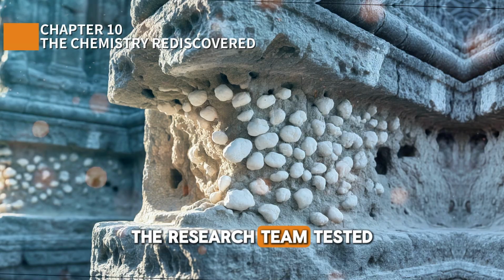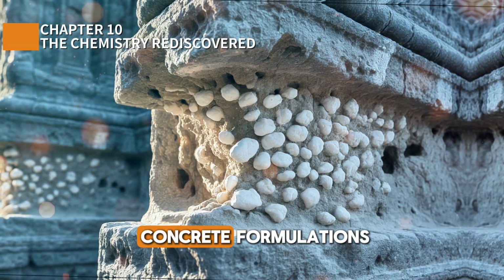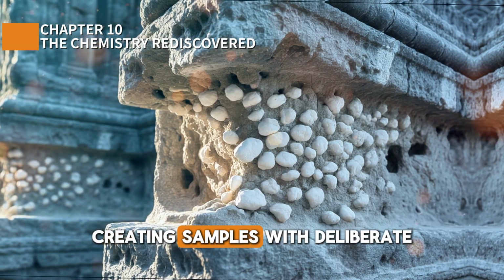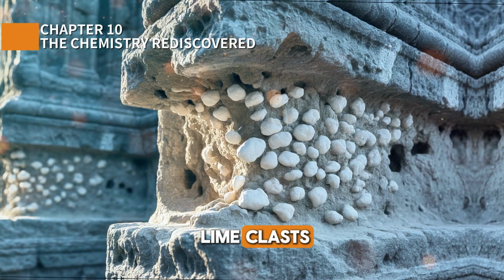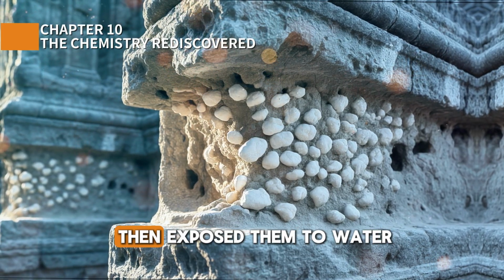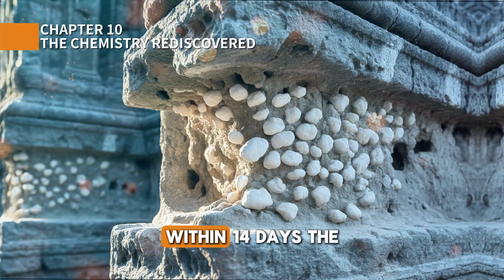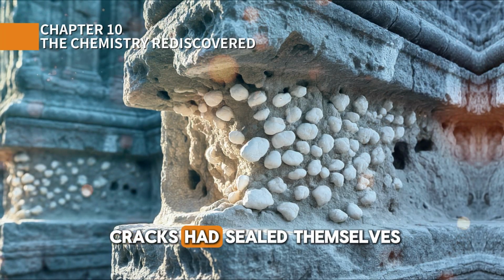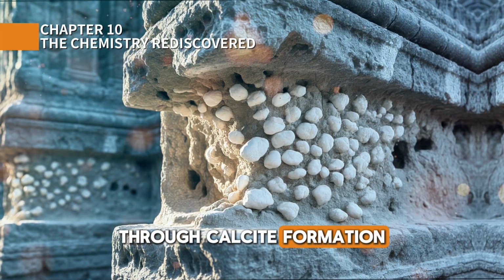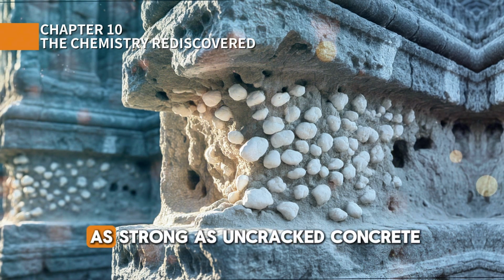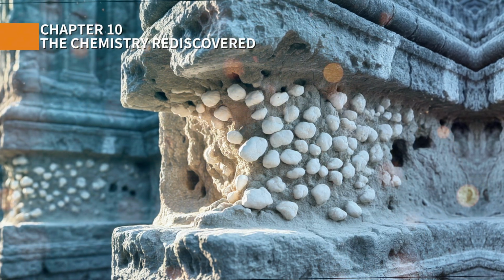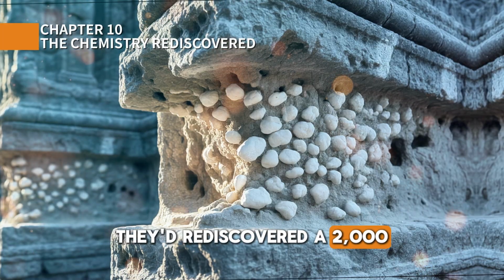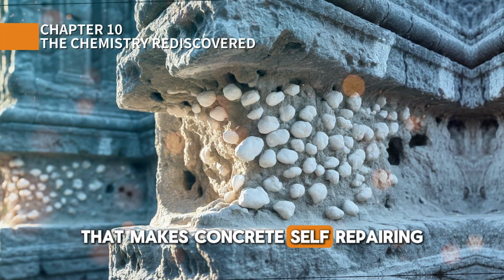The research team tested hot mixing in modern concrete formulations, creating samples with deliberate lime clasts. They cracked the samples, then exposed them to water. Within 14 days, the cracks had sealed themselves through calcite formation. The healed cracks were as strong as uncracked concrete. They'd rediscovered a 2,000-year-old technique that makes concrete self-repairing.